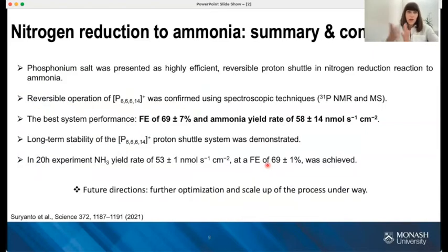So to summarize the whole research, as I showed you, we proved for the first time that the phosphonium salts are highly efficient and reversible proton shuttles for nitrogen reduction reaction. They allow us to produce high ammonia yield rate and Faraday efficiencies. Additionally, we confirmed their stability in long-term experiments, achieving the best results so far compared to other literature reports.